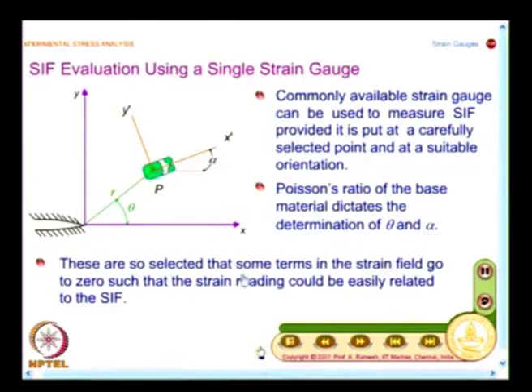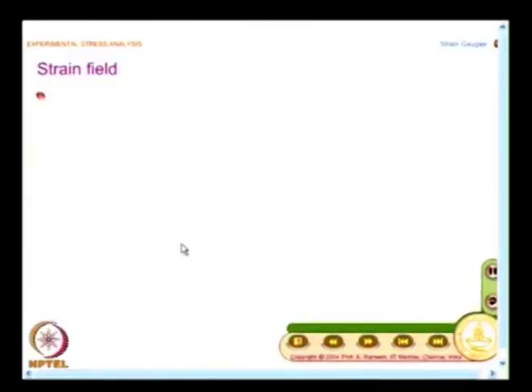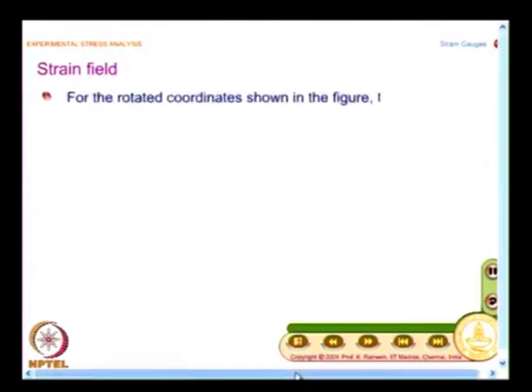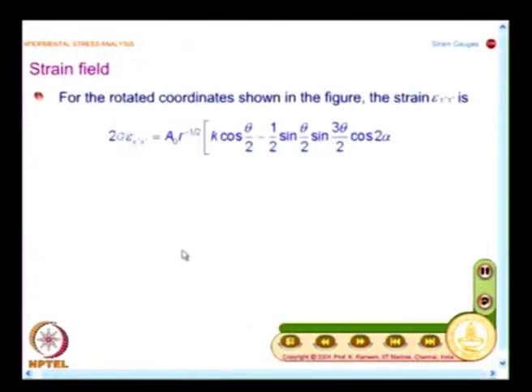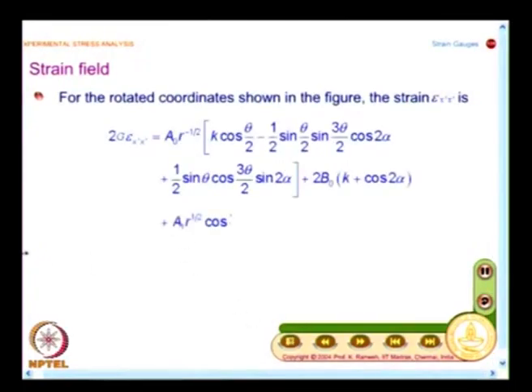so that some terms in the strain field go to 0. So, you have to evaluate theta and alpha intelligently to knock off the terms containing B naught and A 1. So, I will have an expression only in terms of A naught, then I can find out the stress intensity factor from that. And now, for this I need to know the strain along any arbitrary direction. This expression you can write down.